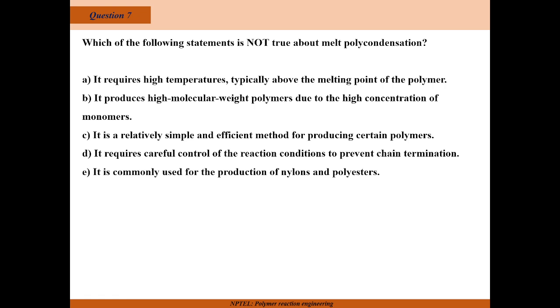One doubt is whether chain termination is really a factor that comes into the picture when we go for step growth. Because some polymers we produce here, we generally leave at a certain stage, like for composite processing. Phenol formaldehyde is produced by polycondensation. We don't allow it to completely undergo the reaction. We stop at some stage.